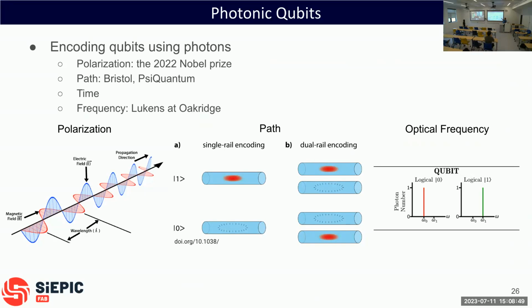And the typical numbers are 3 dB, 4, 5, 6 dB maybe, excess loss. So your transmission through a fundamental unit cell in the system is only 25% for a beam splitter. So it's classical. It's not even quantum anymore.